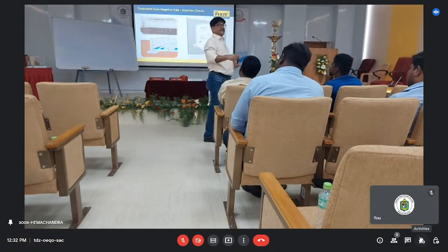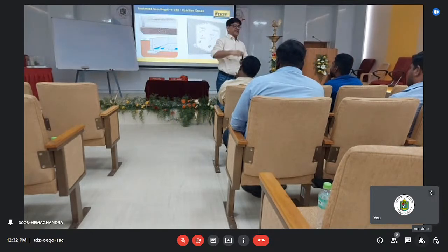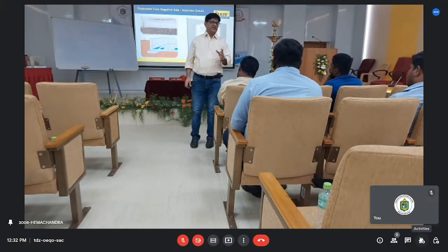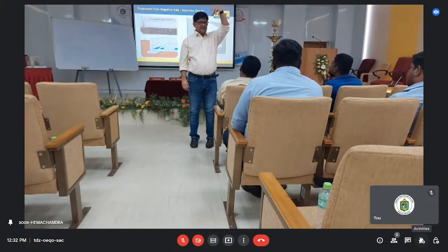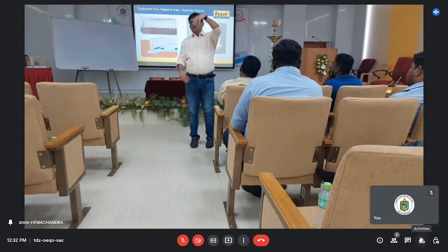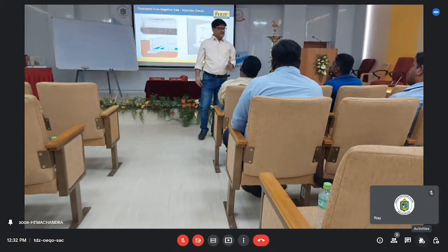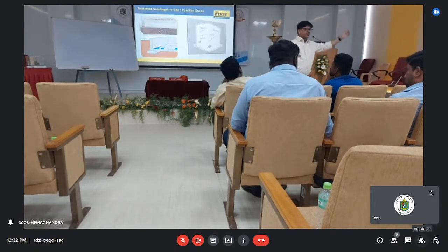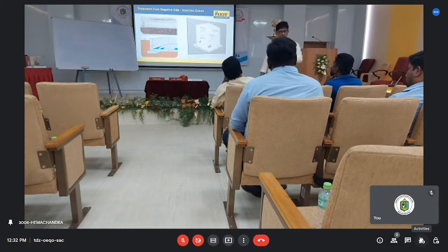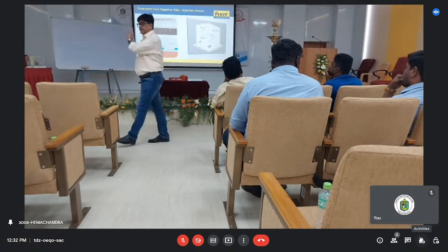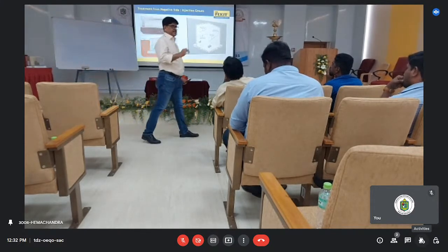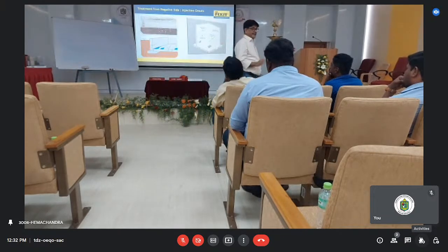Let me tell you very frankly, about negative side on the roof, somebody asked me that I have to do a sealing coat. The sealing coat is just a waste of money. The water is coming through gravity. Whatever you put, tomorrow it will come. Same thing if the water is coming with pressure: if I put something as a coating, it will never hold. So no coating. Whatever coating system or membrane system we discussed yesterday and this morning, nothing is working for your negative side protection.